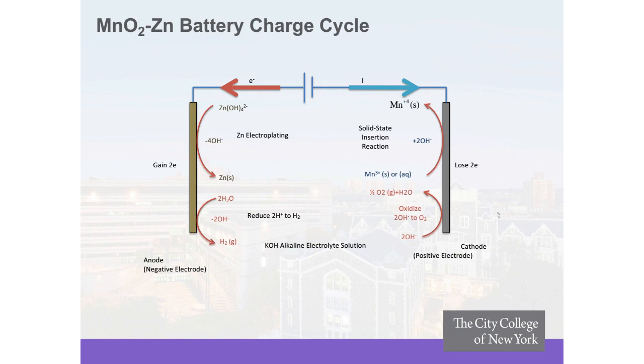These processes, while appear to be very simple, are actually complex in the sense that we do not know what intermediate species adsorb on the metallic surface. We also do not know what the rate limiting steps for these processes are. And at the same time, on the actual anode, there are other competing reactions, such as the electrolysis of water that generates actual hydrogen during this process. And so, in order for us to be able to increase the efficiency of the battery, we need to minimize the parasitic reactions, the electrolysis of water, while figuring out how to overcome kinetic or mass transport limitations during the charge and discharge of the zinc anode during the battery operation.